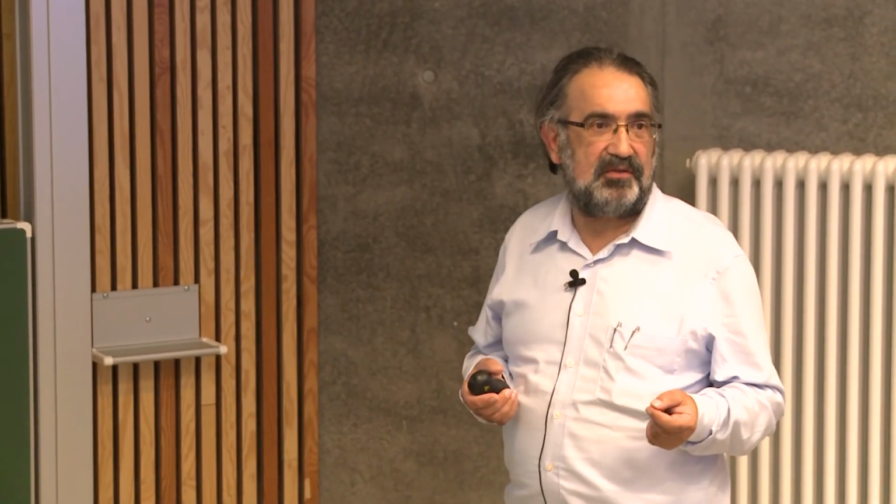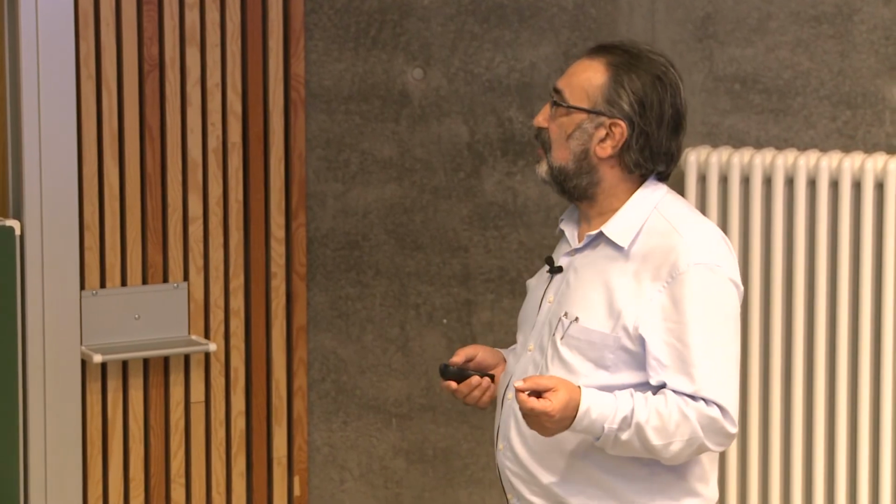So quite often you see that this so-called electrochemical band gap is larger than the optical band gap, because of this overpotential that you need to push in the counter ions. In some cases it fits very nicely, and the optical band gap is exactly the same as the electrochemical band gap. But it can differ.